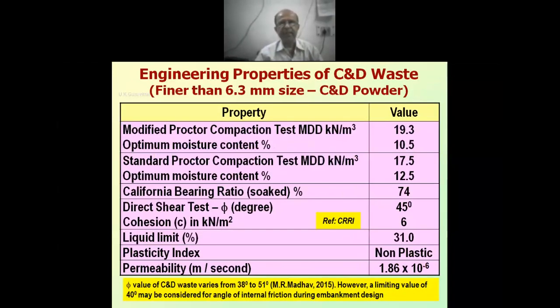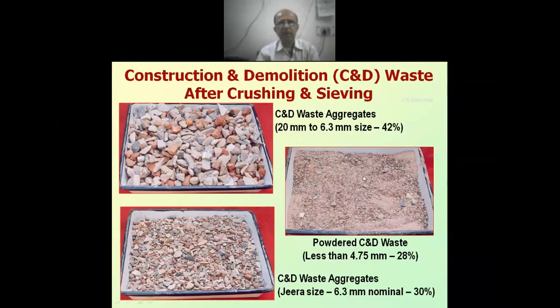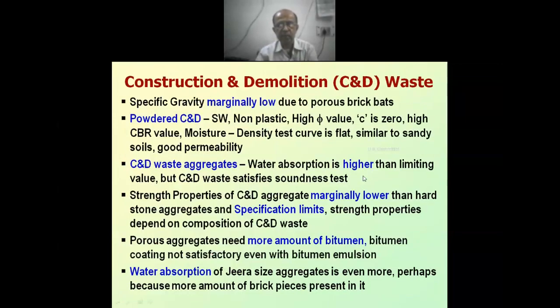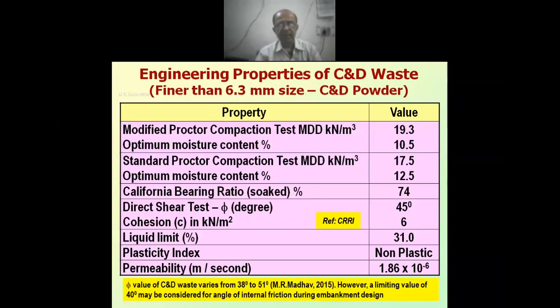Engineering properties of the C&D waste finer than 6.3 mm size, the powdered material. What are the engineering properties of this one? Modified Proctor compaction test: MDD 19.3 kilonewton per meter cube, OMC 10.5%. When we did the standard Proctor compaction, it is 17.5 and 12.5%. CBR value is very high, 74%. So it is a very good material for GSB.